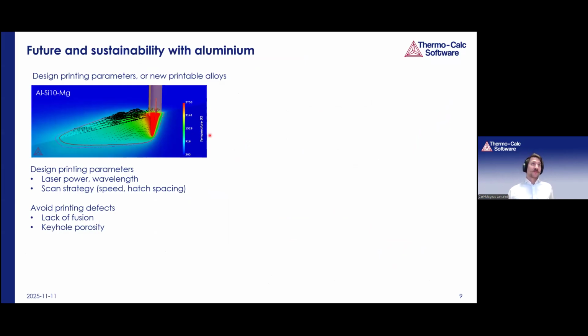It's become more popular to try to qualify aluminum alloys for 3D printing. And we have this integrated additive manufacturing module where we can simulate the laser powder bed fusion process using all of these different properties that I have just showcased. So here we have an example of an aluminum silicon 10 magnesium alloy.